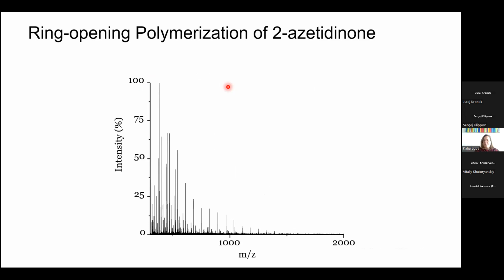So all our polyamide approaches end up with oligomers. So this is our really first approach, and you see also very low molecular weights, just oligomers. We found ways to make this a bit higher with, for instance, supercritical CO2 and ionic liquids, so smart solvents, and in that case also green. But we also found out that it's not so important, because we can always polymerize these oligomers in a solid state post condensation, for instance straight in the extruder, and then spin fibers. But let's say here the highest degree of polymerization would be 19.